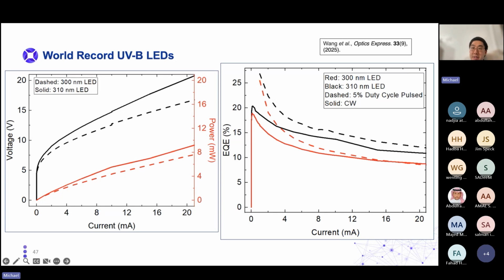And at 5% duty cycle pulse operation, we were able to achieve over 25% efficiency on both of these LEDs at 1 milliamp. We weren't able to go to lower current with the pulse measurement because of the limitations of our setup. But I am sure that the efficiencies at these lower currents under pulse operation would be even higher.